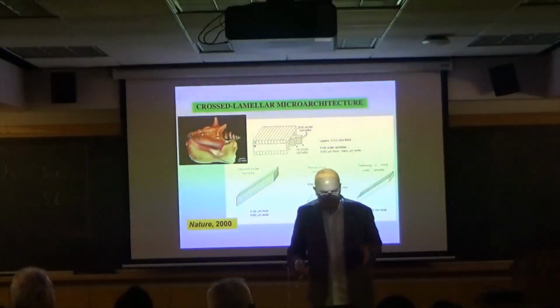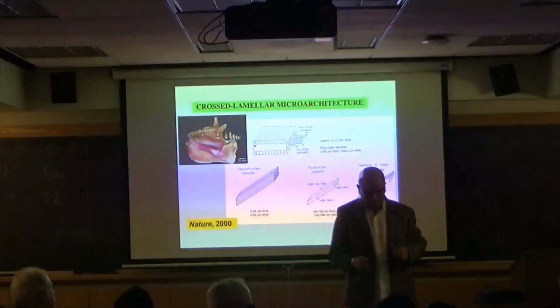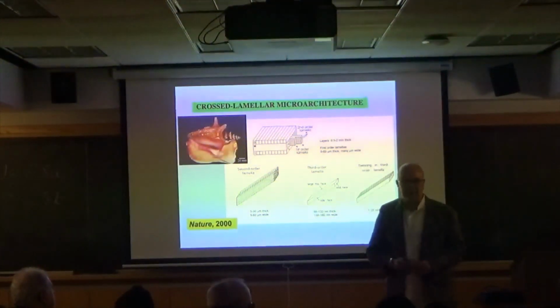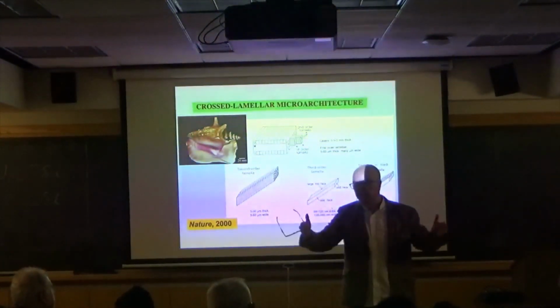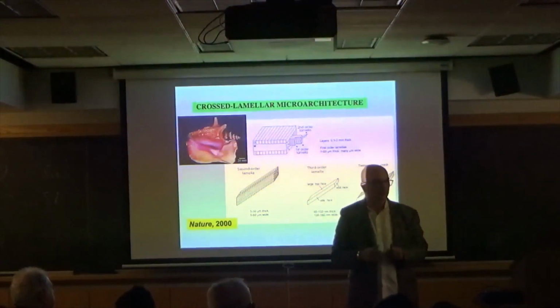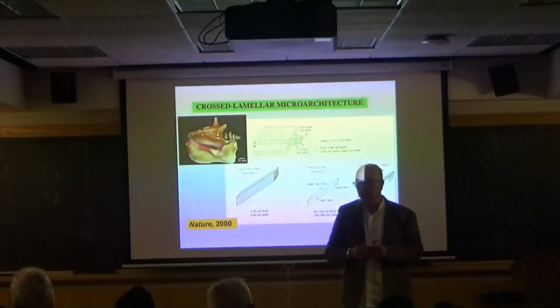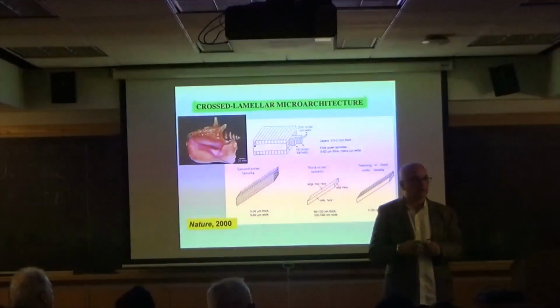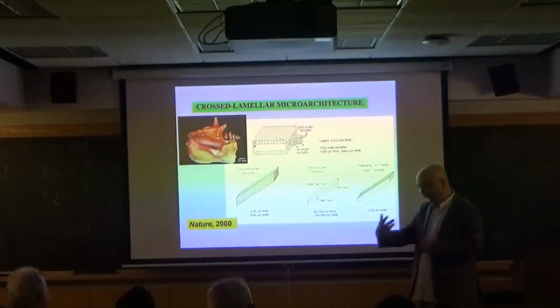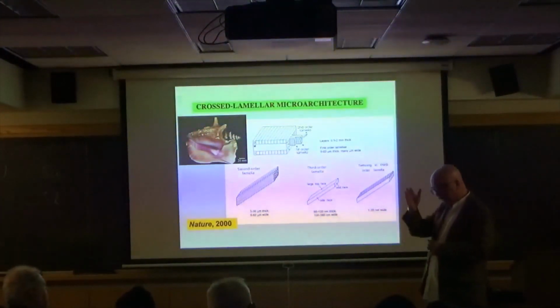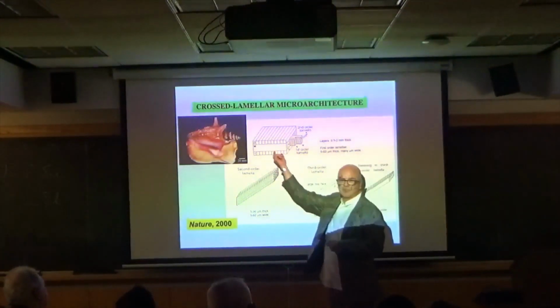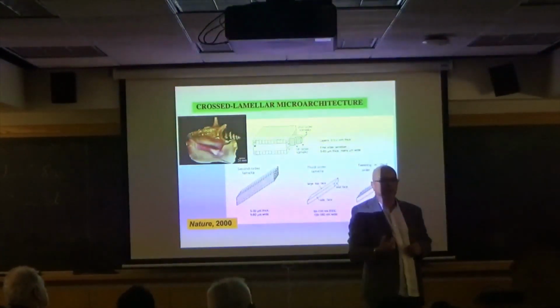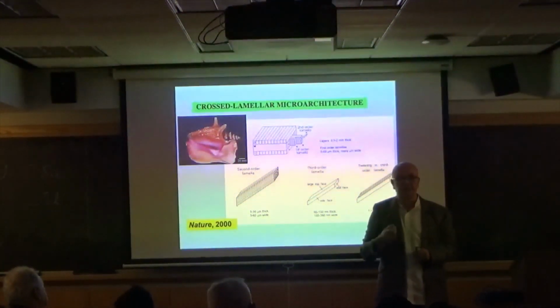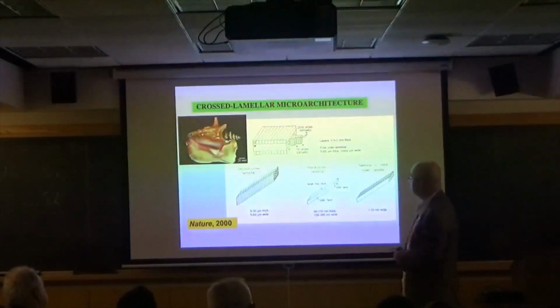In other words, if you were to design a brittle system, you had a ceramic, and you only had one crack in it versus many, many cracks in parallel to each other, which one was stronger? It turns out that when you have many, many cracks, it's much stronger. Okay? Because they shield each other, and you could show that the Eshelby driving force, the configuration force, is a decreasing function of the spacing. So the closer the spacing is, you could actually make the driving force go to zero in the limit. Okay? So how do you do that?